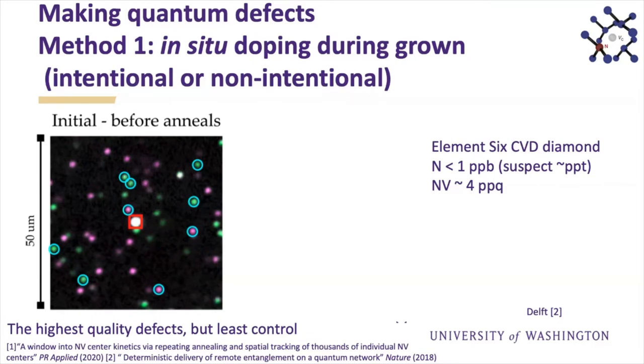And I would like you to look at this. This is a confocal scan. So what's happening is we're using a microscope, and we're scanning our excitation laser, and then we're collecting light. Again, this is with the nitrogen vacancy center in diamond. And where you see a little spot, that's actually where you have one of these point defects in the crystal.